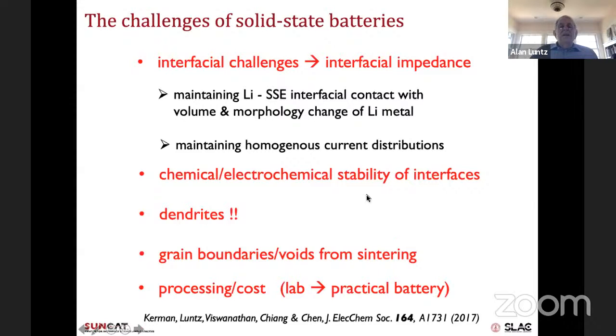The other issue is there's always a question whether the solid state electrolytes are stable against the electrodes. And so that's something that it turns out is not so simple to solve either. And then it turns out that although you weren't supposed to get dendrites, you do get dendrites in these things. And so there's some different mechanisms for growing dendrites, which have to be understood.